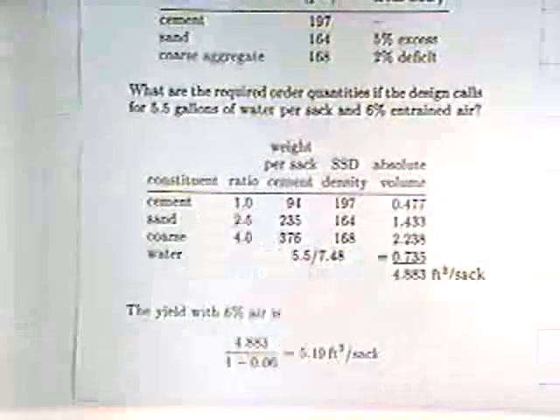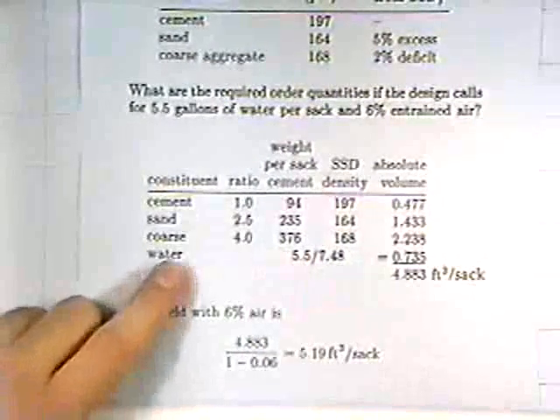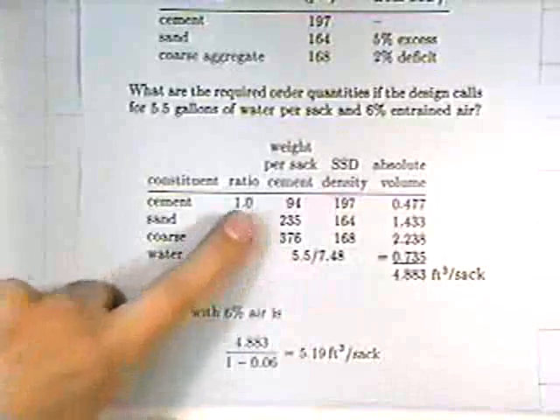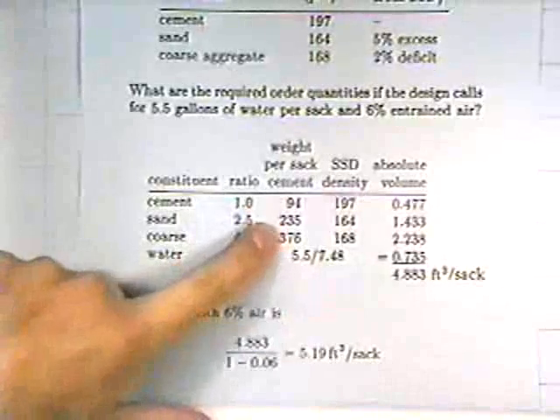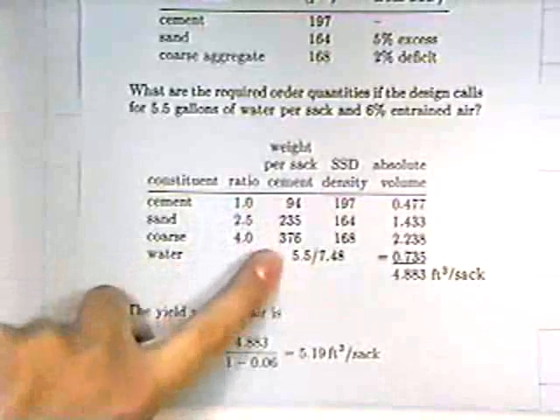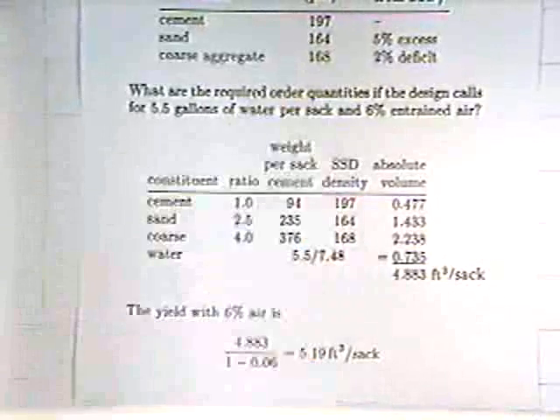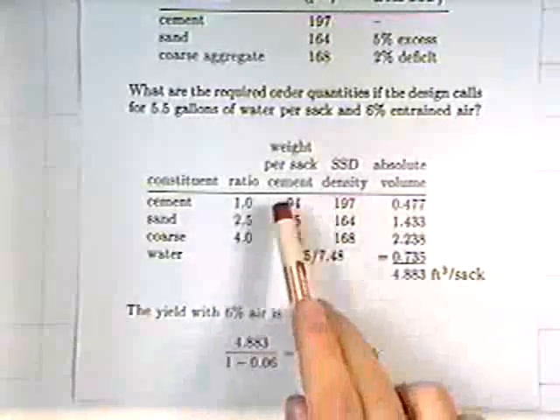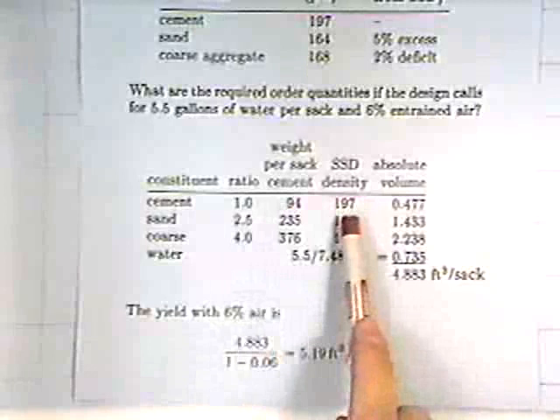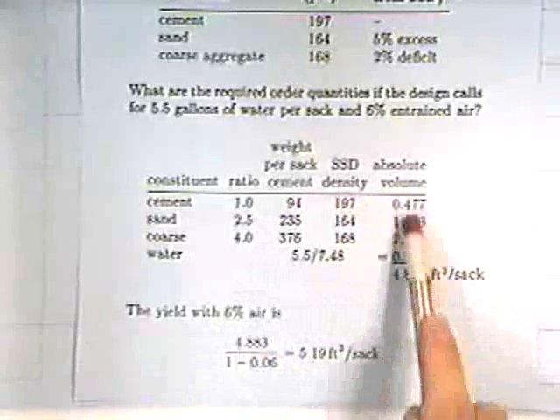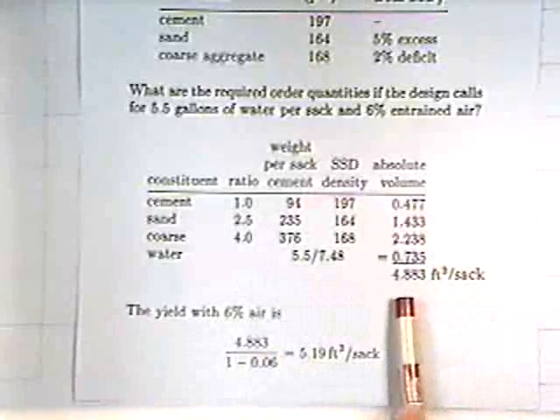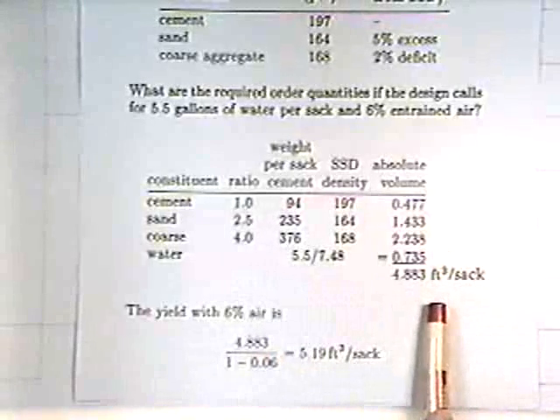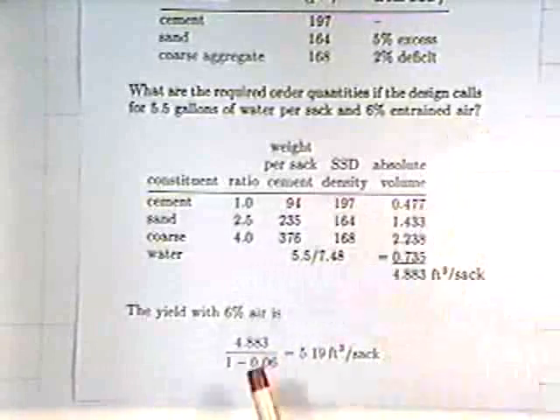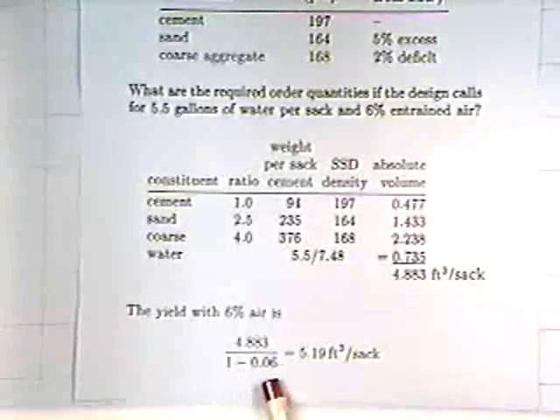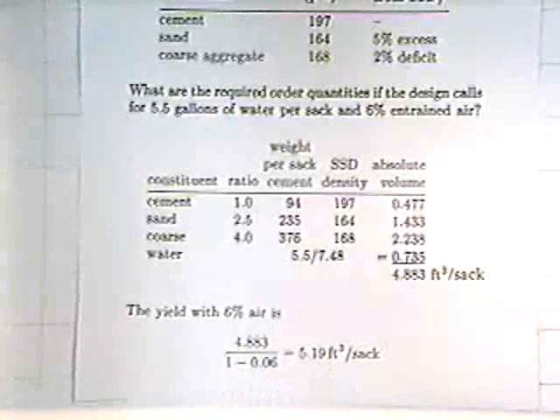Again, set yourself up a little table here. You've got cement, sand, your coarse aggregate, and your water. The ratios are 1 to 2.5 to 4. The weight per sack we know is 94, 235, and 376. Saturated surface dry you find from the previous table, and if you divide the third column by the fourth, you get the amount of volume, and when you add it all up, you get your total yield. This turns out to be 4.883 cubic feet per sack. Because we're adding air, we're going to increase that yield. So we divide by 1 minus 0.06, and you come up with about 5.2 cubic feet per sack.